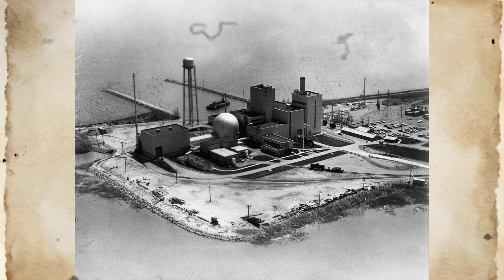The thermal response of a blocked fuel assembly followed heat transfer principles that were well understood from reactor safety analysis, but the rate and extent of temperature increase depended critically on the degree of flow obstruction and the specific power generation rate within the affected assembly. Complete blockage of coolant flow would cause fuel temperatures to rise to damaging levels within minutes, while partial blockage would result in more gradual temperature increases that might not immediately exceed fuel damage thresholds but could cause cumulative damage over extended periods. The metallic uranium fuel used in the Fermi 1 reactor had thermal properties that made it particularly vulnerable to damage from overheating, compared to the ceramic uranium dioxide fuels used in most commercial reactors.